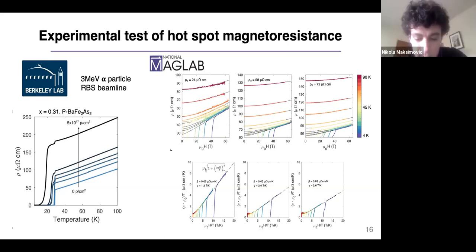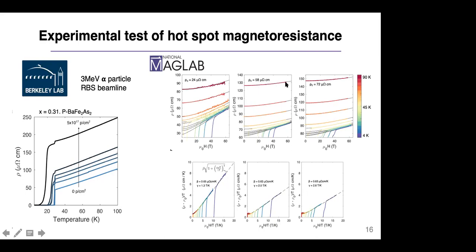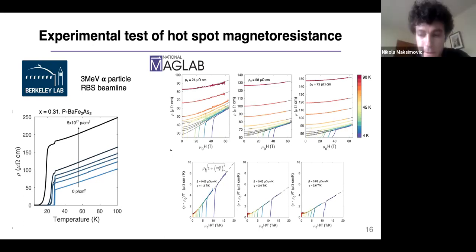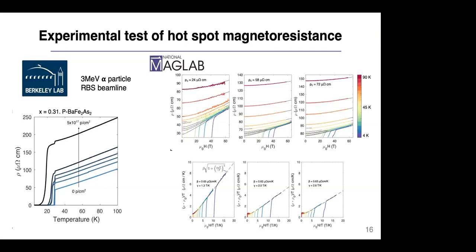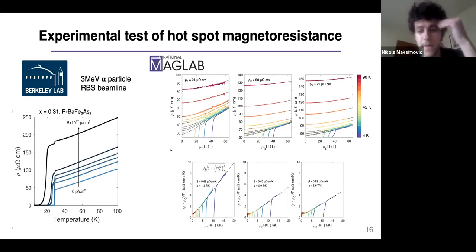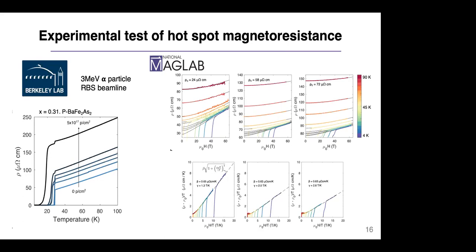I mean, to some extent, it depends on what temperature you're measuring at. So if you're at high temperature, you do see a B squared variation. So I am speaking of measuring cases which are near the optimum TC in the cuprates. Yeah, I know there's been certain cuprates, I think LSCO, where there's a linear magnetoresistance near the optimal TC. We also see it in very overdoped cuprates as well, the appearance of this linear magnetoresistance at high fields. But I think your point in YBCO is clear that it's mostly quadratic there, but it might be the field scale, as Nikola said. This is very strange, a very big difference.